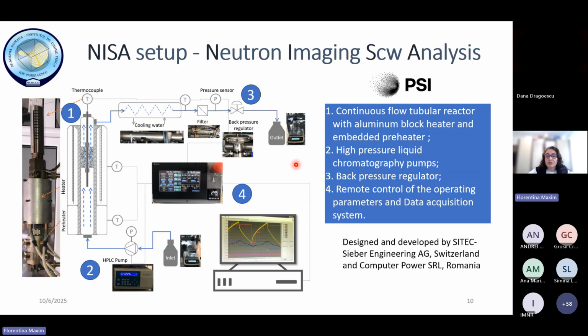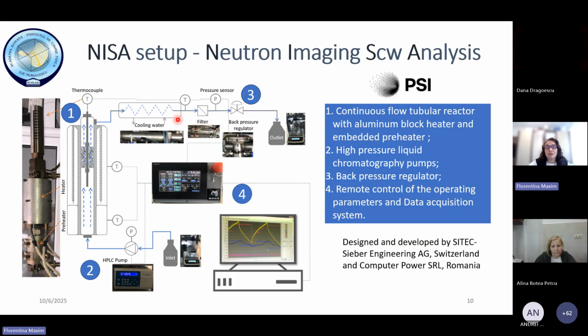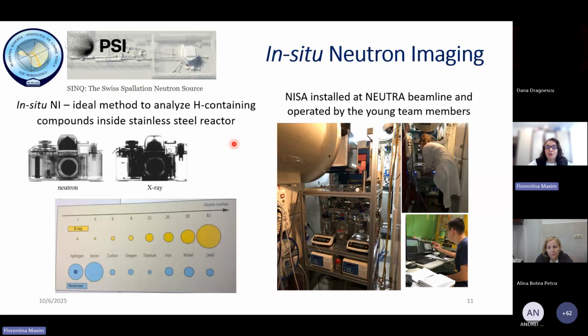The main components of this setup are the continuous flow tubular reactor, with embedded heater and preheater. The fluid is fed into the reactor upwards by high pressure liquid chromatography pumps. The pressure in the system is built and controlled by the back pressure regulator, and the whole system is remotely controlled, with data acquired via data acquisition software every 10 seconds. As I said, we based most of our experiments on in situ measurements using neutron imaging.